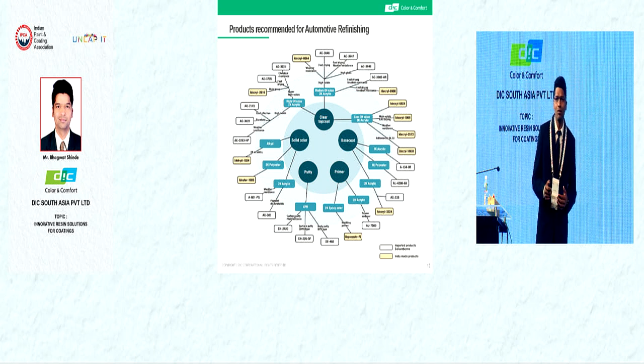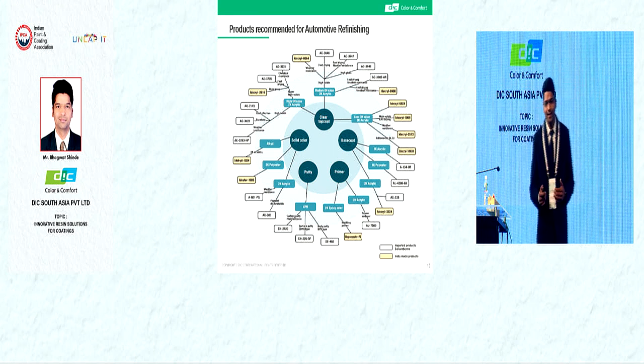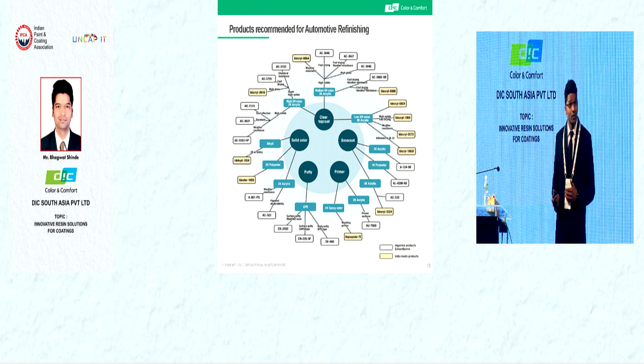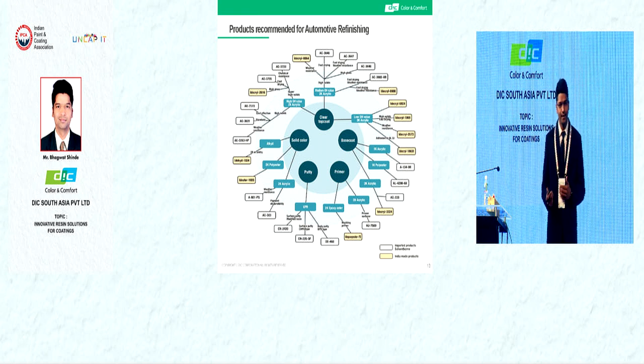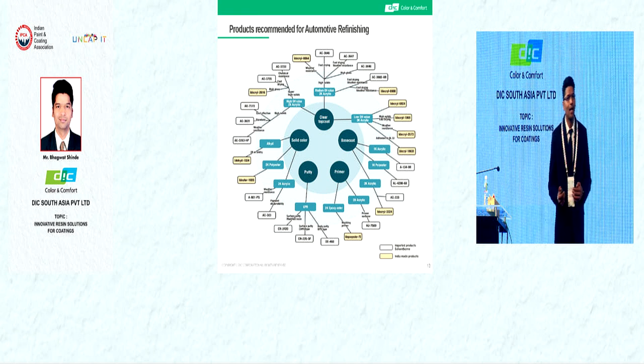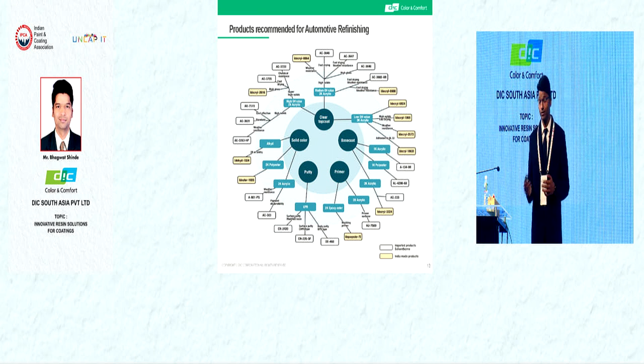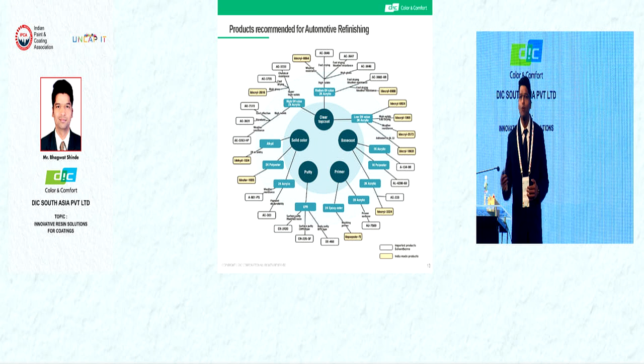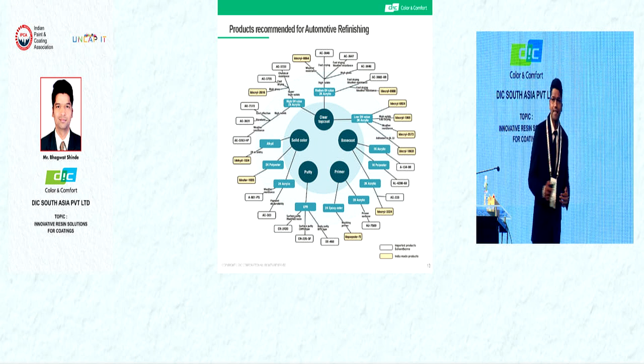Here is the product lineup for automotive refinishing coatings. We have products for the putty, primer, base coats, and clear coats. For the putty, we have both body putty and surface putty. For the primer, we have 2K acrylic resins for the primer surfacer and 2K epoxy esters for the washing primer. In the base coat region, we have 1K acrylic, 2K acrylics, as well as 1K polyester and alkyd resins. For the clear top coats, we have 2K acrylic resins, mainly divided by the hydroxy value. As I mentioned, the hydroxy value plays an important role in chemical resistance as well as gloss and other weather properties. So we have products categorized in three segments: economy, middle, and premium segments.